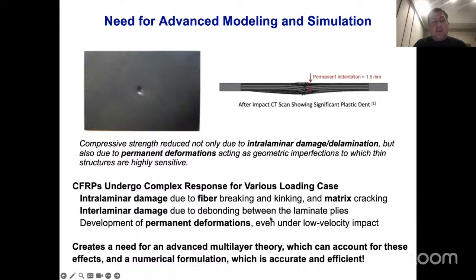When we look at CFRPs, as we all know, they undergo complex response for various loading cases. Intralaminar damage due to fiber breaking and kinking, matrix cracking, interlaminar damage or delamination due to debonding between the laminate plies. And another aspect that's perhaps not so appreciated is the development of permanent deformations, okay? Kind of a plastic-like response, even under low velocity impact.